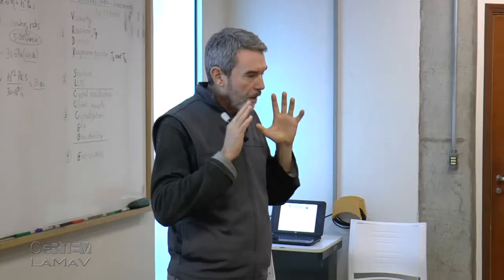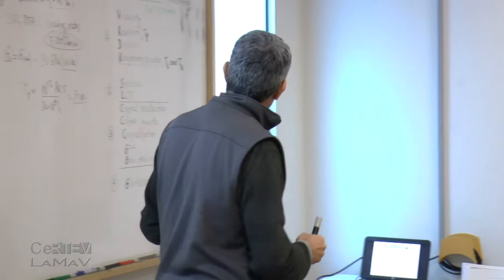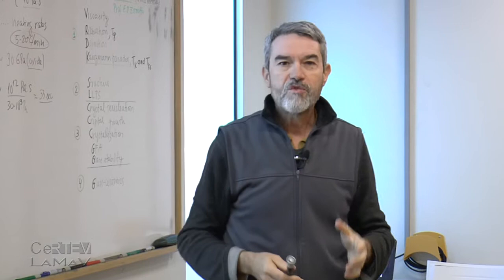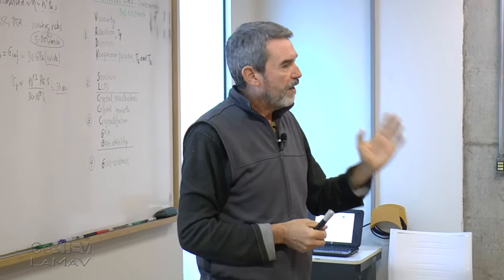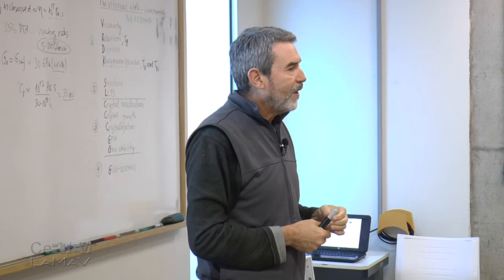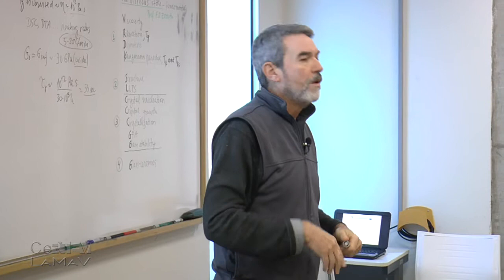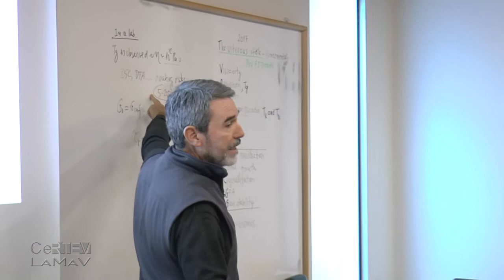So I'm trying to make clear that Tg is not a thermodynamic temperature, like the liquidus, or the melting point, or the transformation of alpha quartz to beta quartz, 573 degrees Celsius. You cannot define Tg for any material. You can say Tg is approximately 550 degrees Celsius for a soda lime silica glass, as detected by DSC at this rate here.